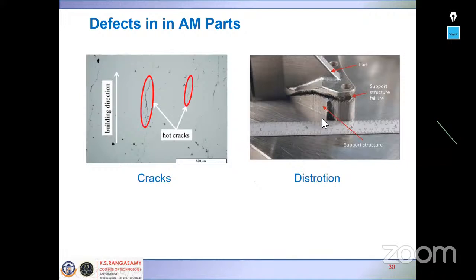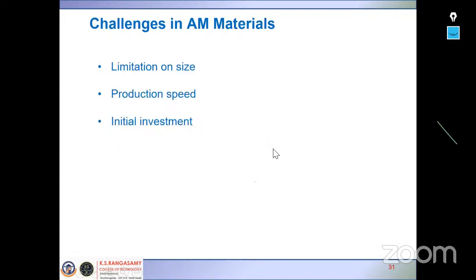So the distortion is another defect in the material, due to volume shrinkage. This distortion will take place in the 3D printed components. The other challenges are the limitations on size. The build environment platform is another challenge, because you have a minimum size. Even if you have a very big machine of, say, 1,000 mm by 1,000 mm by 1,000 mm, I visited CPET, and the machine costs around 5 crore, and the build environment is like 900 by 900 by 900. So the size is another limitation, and the production speed is also a challenge, as is the initial investment on the material and on the machine, which is a high cost.